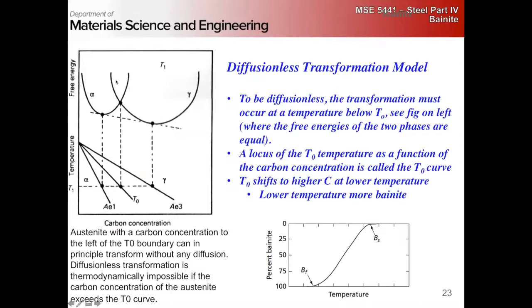But really the argument is my free energy when I go from austenite to ferrite had better go down without partitioning, right? So what happens? I can go from here, I can drop to here, I'm still at the same concentration, then I will partition into ferrite of this composition and austenite of this composition, right? Or I can grow cementite, right? That's not on here as well, right?